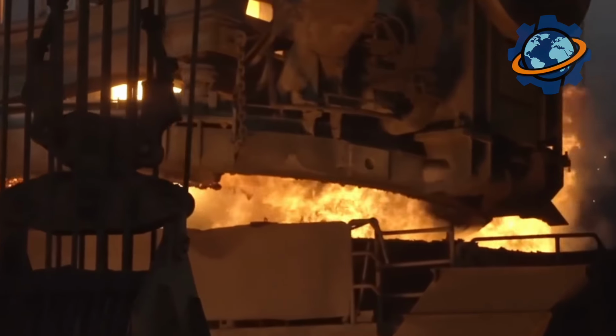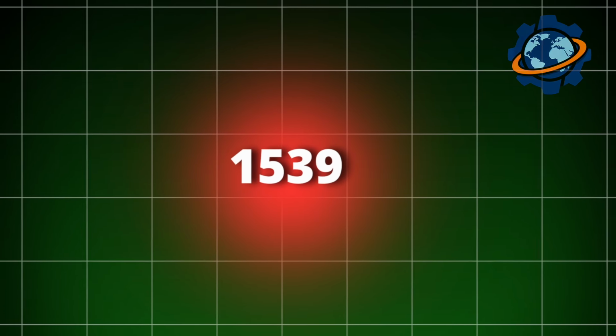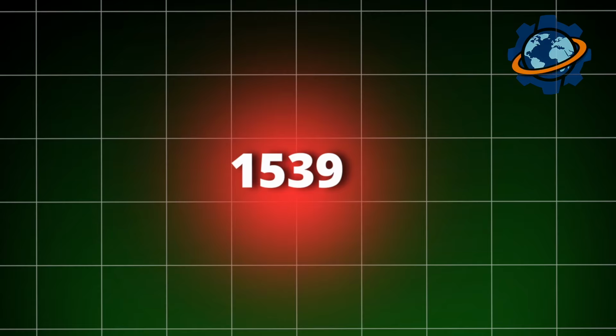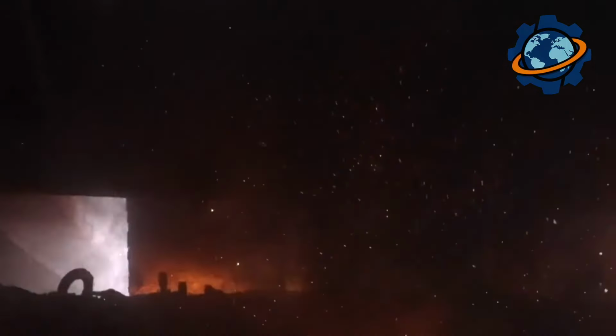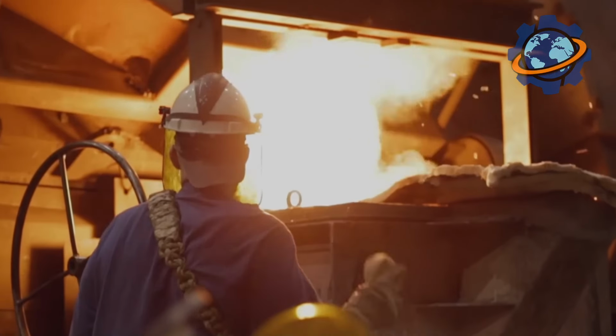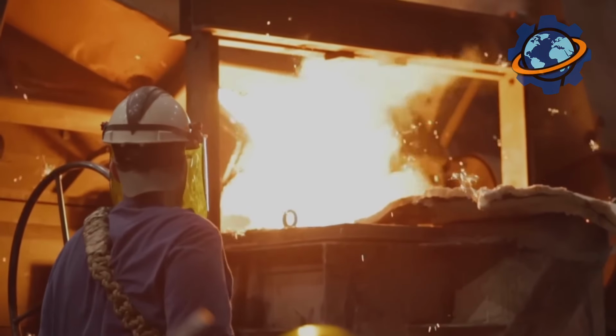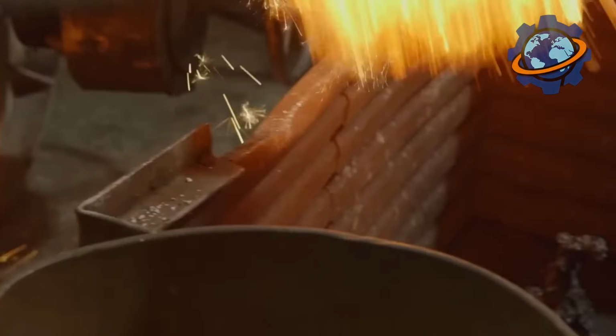Pure iron melts at a very high temperature of 2,800 degrees Fahrenheit, 1,539 Celsius. But soaking up carbon dramatically lowers that melting point. That's why a blast furnace doesn't produce pure iron, but an alloy of iron and carbon, pig iron, which becomes liquid at just 2,200 degrees Fahrenheit, 1,200 Celsius.